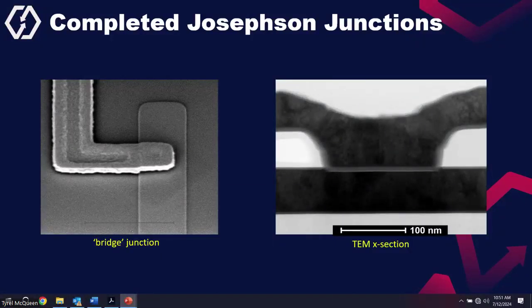So this is a bridge junction. This tantalum layer is forming a bridge. This tantalum wire is going to the 4-probe structure, and the junction is here basically. So this is the bottom electrode line. Then there is a barrier there which is not visible here, but it's visible as a hole here. And then this is the top electrode. And here is the TEM cross section showing the bottom tantalum, top tantalum, and insulating barrier.